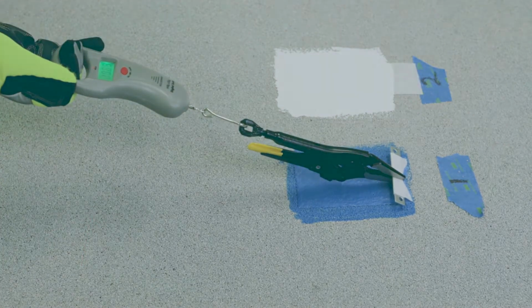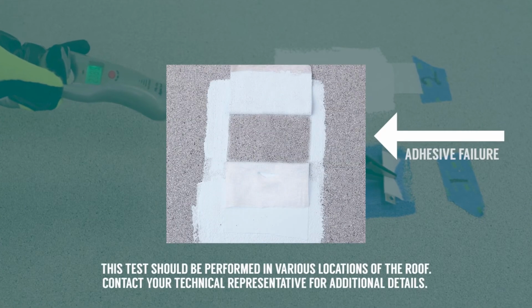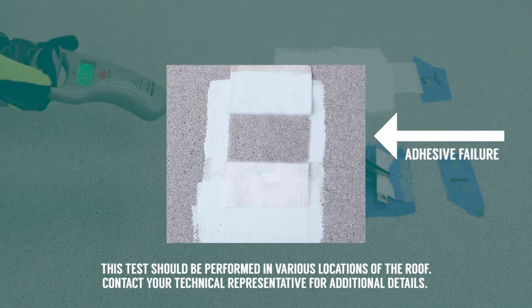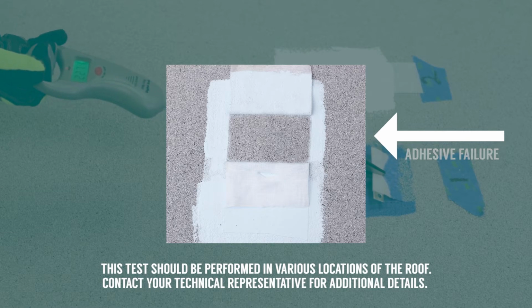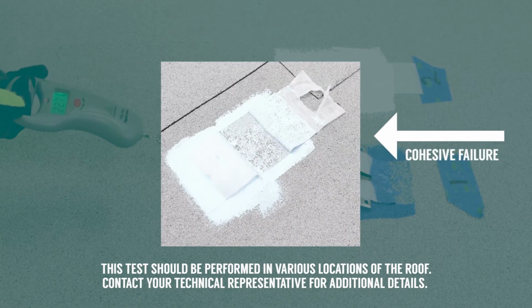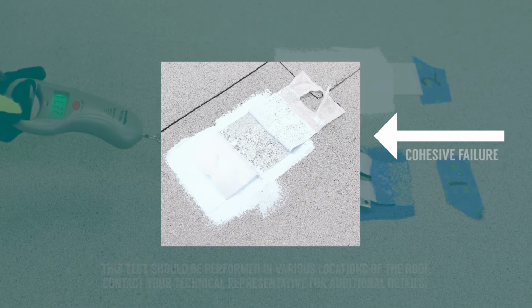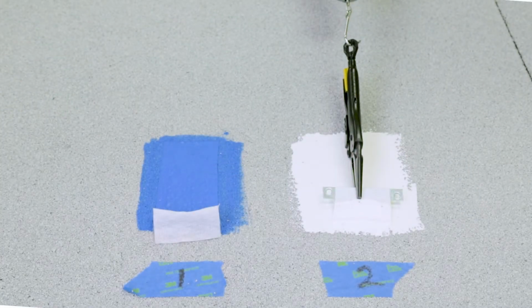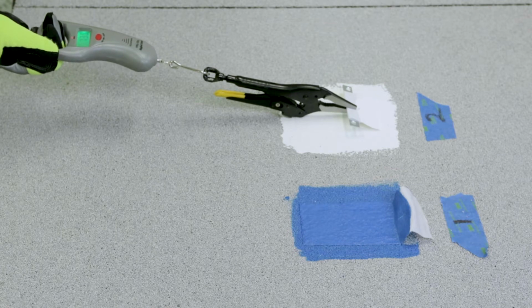If the coating comes off the substrate clean, adhesive failure occurred and a primer will likely be required, depending on the strength of the pull at the time of failure. If coating is left on the surface, it is possible the primer may not be required. The same test can be done with additional primers. For best results, a primer is recommended. Be sure to consult with Polyglass Technical Services if you have questions regarding the field adhesion test results.